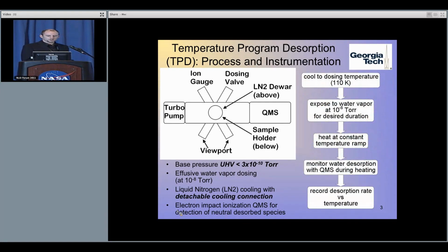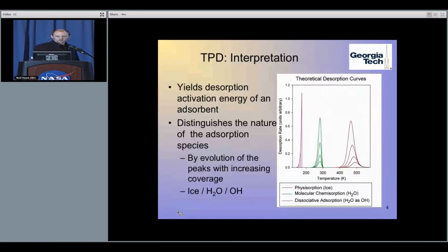So the actual experimental flow using this chamber is we deposit the powder, put it in full vacuum. Then we cool to a dosing temperature of 110 Kelvin in most cases. We expose the sample to the desired amount of water vapor. We then heat at a constant rate of temperature with time, monitor the water desorption with the quadrupole mass spectrometer, and record the quadrupole signal, which is the desorption rate versus temperature.